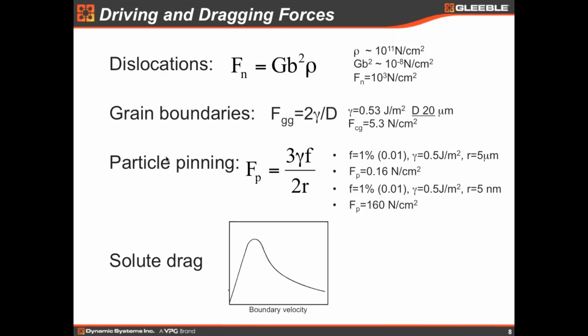Well, the driving and dragging forces. Firstly, the main driving force for recrystallization is the dislocations, and it can be calculated using this equation. We've seen these equations a million times in papers and books, so I'd like to have some numbers for all these quantities. So this is the shear modulus, the Burgers vector, and the dislocation density, and we can have an example. This driving force for recrystallization due to the dislocations will be, let's say, 1,000 Newton per centimeter square.